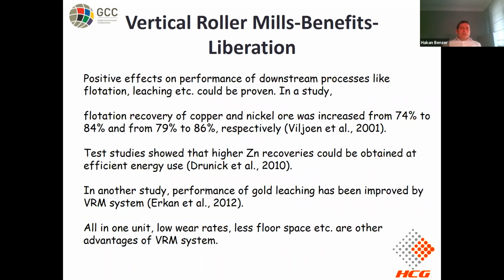Also, some researchers indicated positive effects on the performance of downstream processes like flotation and leaching. In one study, it's been proven that flotation recovery of copper and nickel was increased from 74 to 84%. And also, again, zinc recoveries could be obtained at higher levels, at efficient energy use.